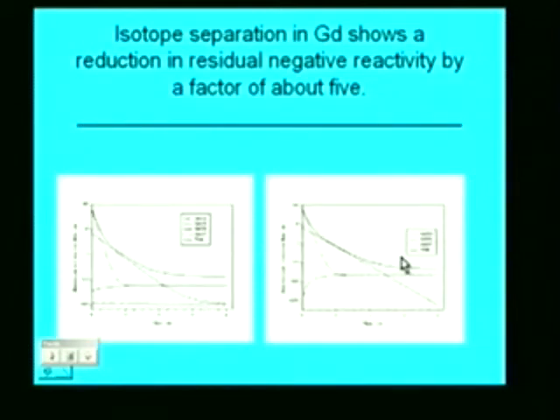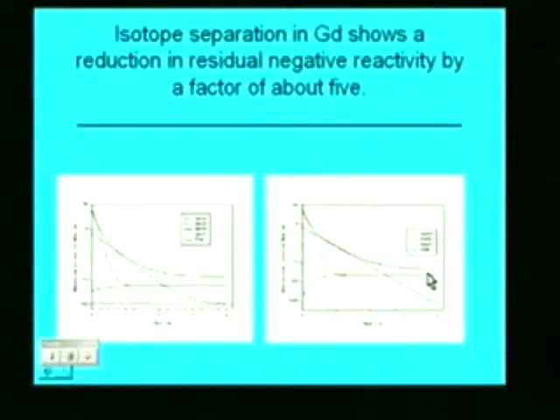Well, we could remedy that by isotope separation. An example here is again gadolinium. Over here we plotted the macroscopic absorption cross-section as a function of time. If we look at the total, we notice after about 3 or 4 years, we end up with the residuals in a steady state around 0.15 or so. And in this case, we have removed the gadolinium-155 and 157. In that case, you can see that the residual is lower by roughly a factor of 5.